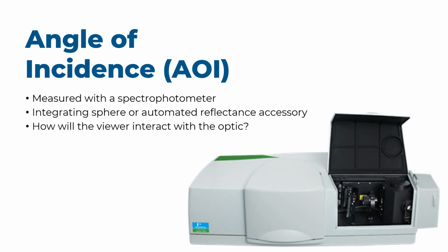Another requirement is angle of incidence. Angle of incidence is basically how is the user or how is the sensor going to interact with the light off the surface. This is also measured with a spectrophotometer. There are some automated and more mechanical ways that this can be measured. An automated way to measure this would be using an automatic reflectance or automated reflectance accessory. The other way would be an integrating sphere, which is more of a mechanical sort of solution. And really finding out how you're going to interact with light is vital to specifying angle of incidence.